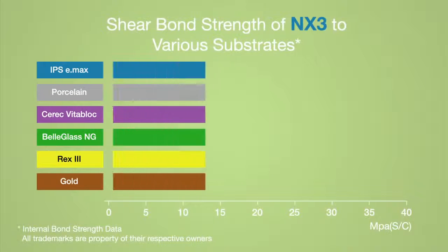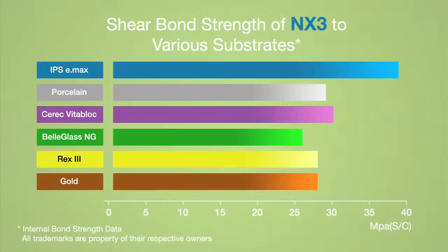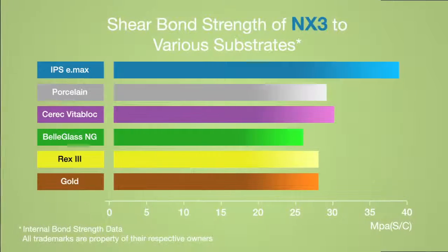Looking at this chart that publishes the shear bond strength of NX3 to various substrates, you can see how well the material performs. The thing that's most surprising to me is how well it bonds to gold, but predominantly most of my work is Emax, lithium disilicate, and ceramic restorations, both CEREC and lab processed ones, and they're clearly above the acceptable range for bond strength.